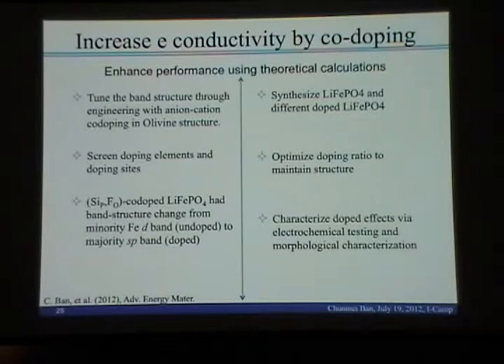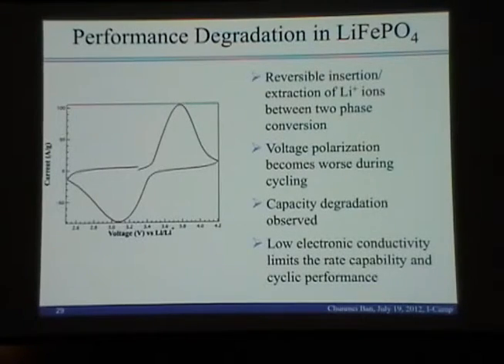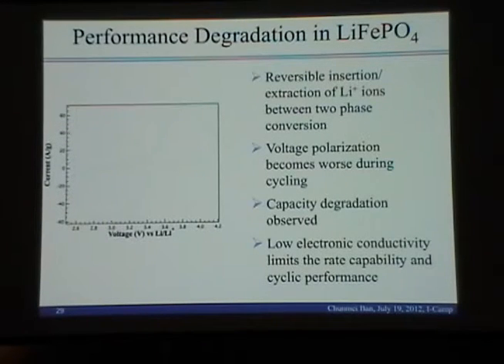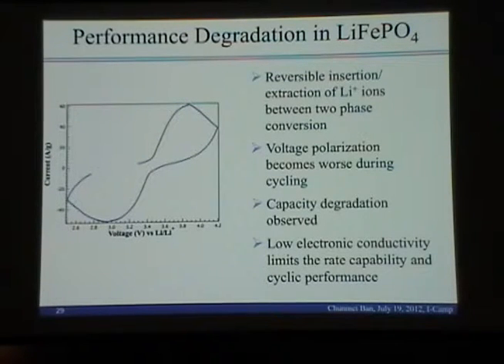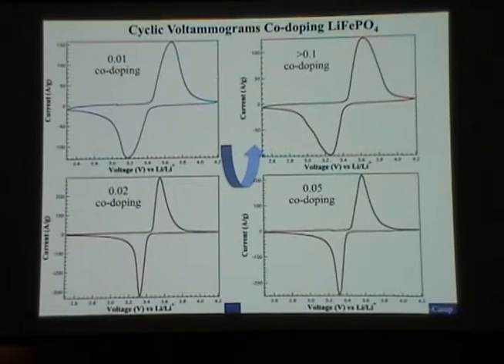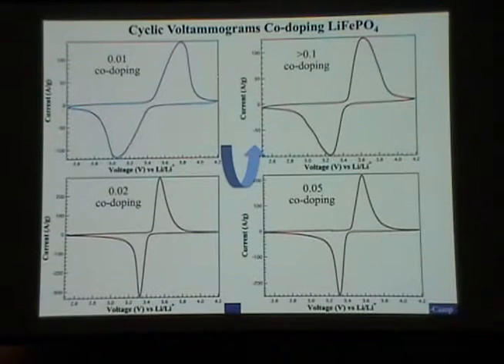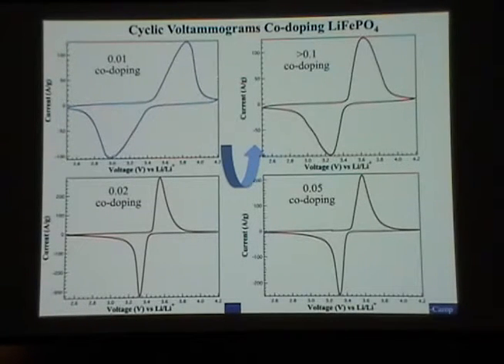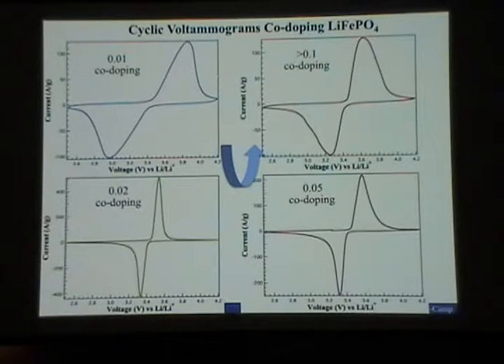So they can dope the material with different valence transition metals. For example, in this case, we use different doping to increase the electroconductivity. So this one shows pure lithium iron phosphate, and this is a CV plot showing how it degrades. And then we dope this material at different levels. For the low level, it is similar to the bare lithium iron phosphate, and at a little bit higher level, you can see the peak is very sharp and the reversibility is really good.